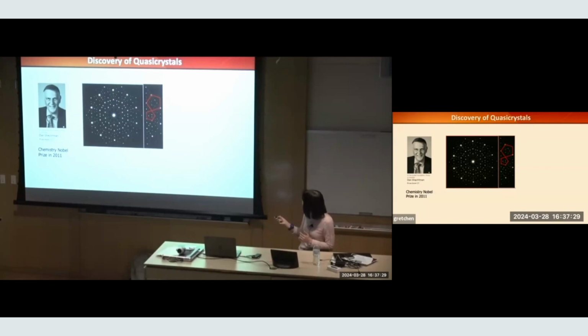The important thing to realize is that he had a hard job. It was very difficult to convince people because he only had these diffraction patterns, and you actually need to analyze a diffraction pattern where the intensity can be 5 orders of magnitude different from an adjacent diffraction peak. You not only need really good quality samples, you also need really good measurement. Nobody believed him for a long time. He couldn't get his paper published anywhere for 2 years. Eventually, it got accepted. He got a Nobel Prize. But looking at this diffraction pattern and asking where the atoms are in real space is still a challenge.